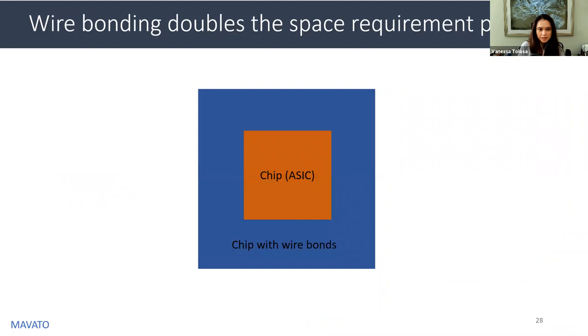The problem is this takes up too much space. So with wire bonding, it doubled the area that the chip alone had to take. So going from 2 mm² to 4 mm² when you add the bonds. And since for this particular project, we were aiming to eventually go up to 10,000 channels, we needed a different method.